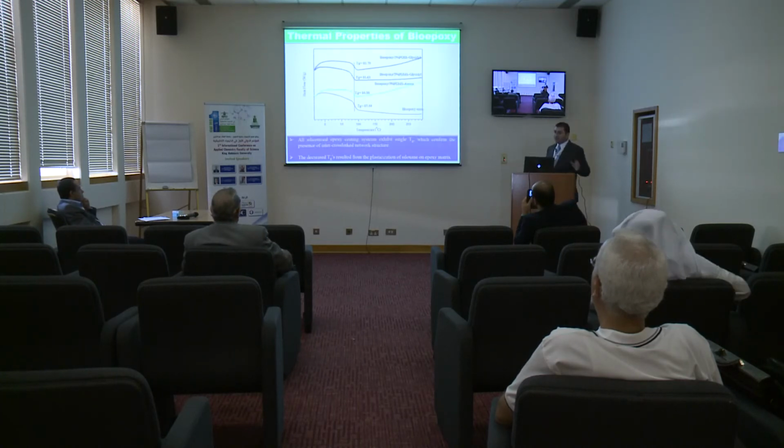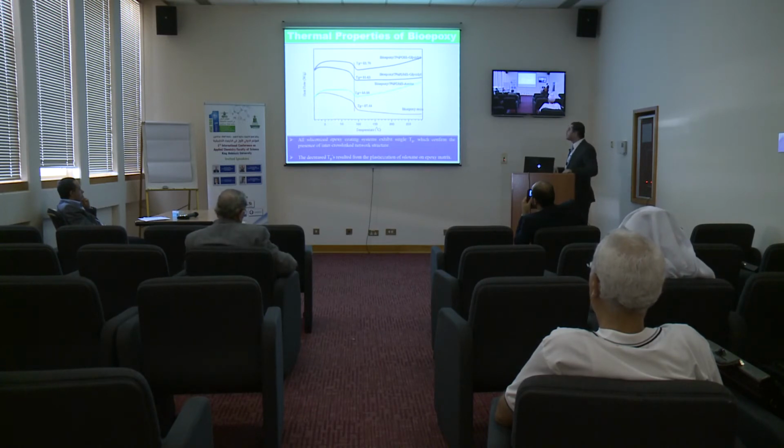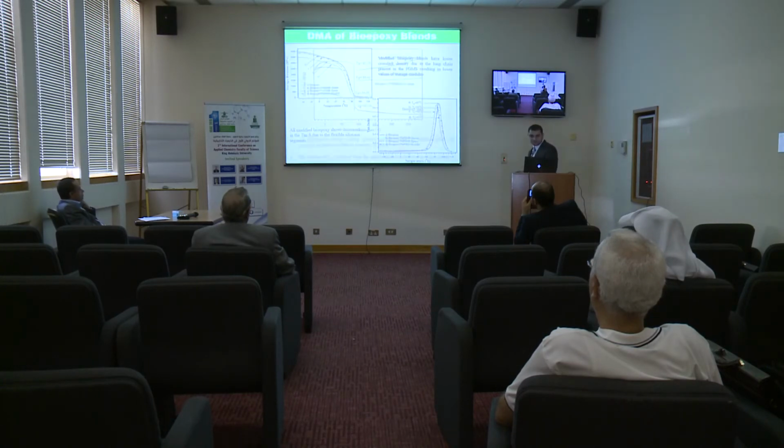We also measured some thermal properties and saw that the glass transition temperature is decreasing, indicating good homogeneity between the bioepoxy resin and POSS-glycidyl. In the dynamic mechanical analysis for viscoelastic behavior, we found that all the bioepoxy blends decrease compared to the neat bioepoxy, and the glass transition temperature from the tan delta curve gives almost the same value as the DSC.